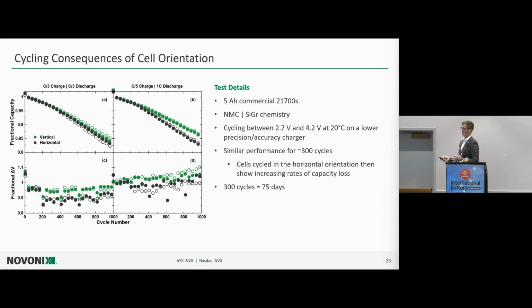So this is discharge as the materials relax within the cell, electrolyte comes back into the jelly roll. There's not as much time for the electrolyte to get in, equilibrate, and the concentration gradients to equilibrate within the cell. And what we see is the cells positioned vertically perform a lot better, and the cells horizontally do a lot worse. And again, this takes 300 cycles or so to start seeing this difference.